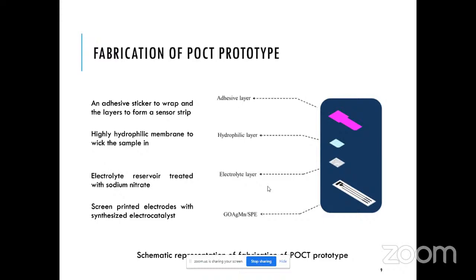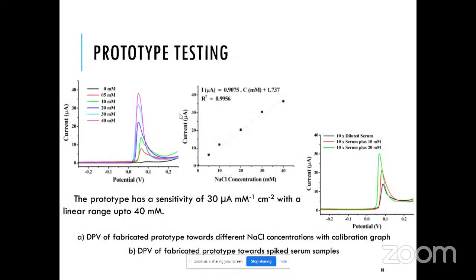And finally, we have an adhesive sticker. It is used to wrap and seal all the components together, and it forms a point-of-care testing prototype. And this prototype is tested with different chloride ion concentrations, and we can see that in a range of 0 to 40 millimolar, we are seeing a linear increase in current response, and the sensitivity of the fabricated sensor is 30 microamps per millimolar per centimeter square.